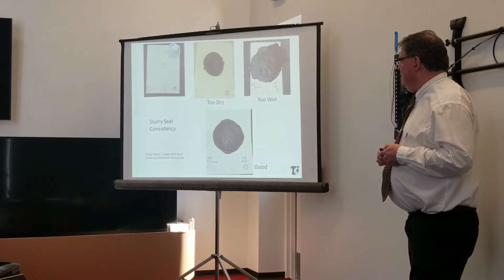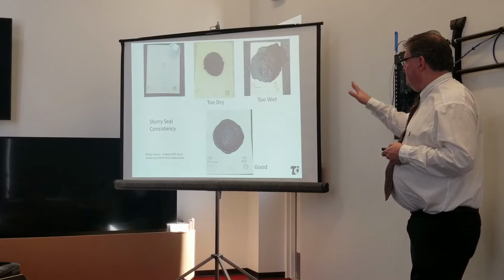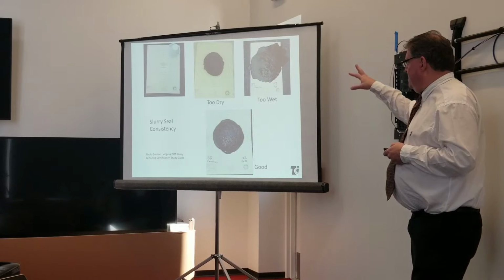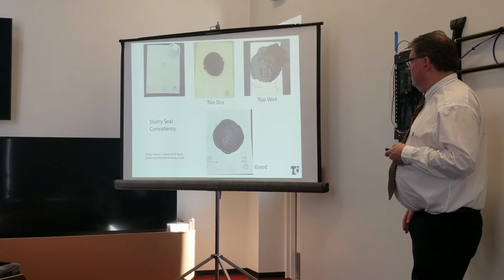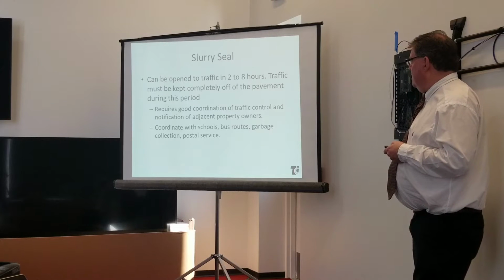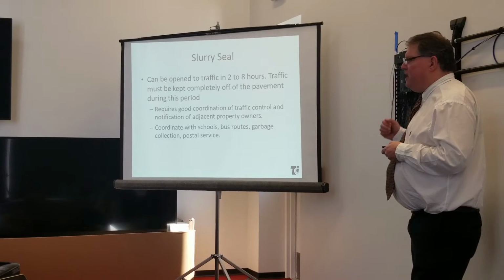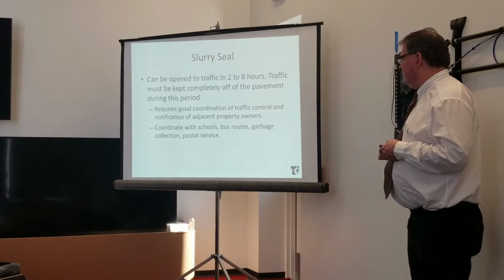Another example there, you don't need that many people working, that was a demonstration. And this is just showing a little demonstration of how the material should look. Right? The bottom one there is about how that material should look. It shouldn't be as dry as you see on the left and the top, and it's way too wet on the right. So maybe 2 to 8 hours, depending on your environmental conditions, you're going to get this open, and a little bit depending on the mix design.